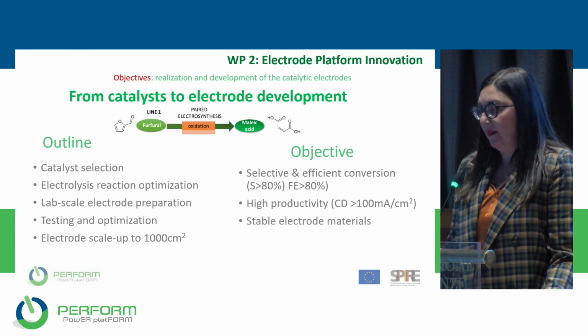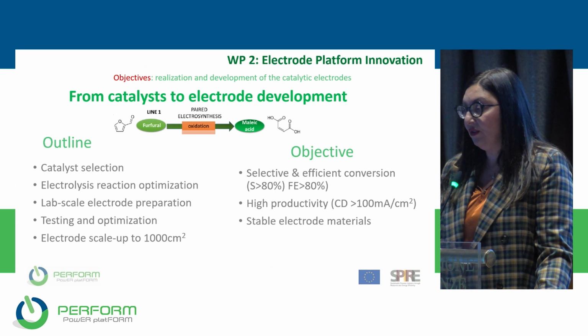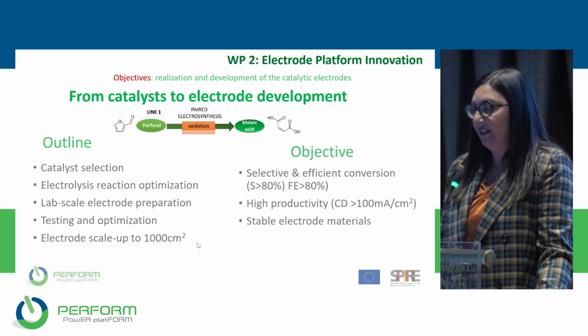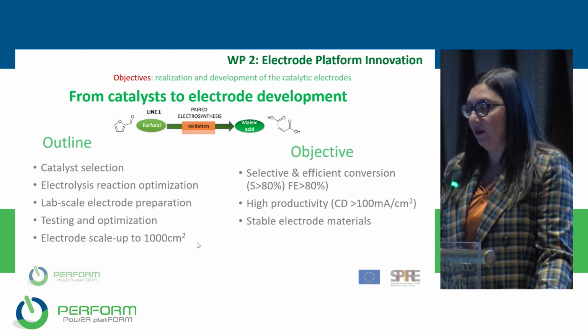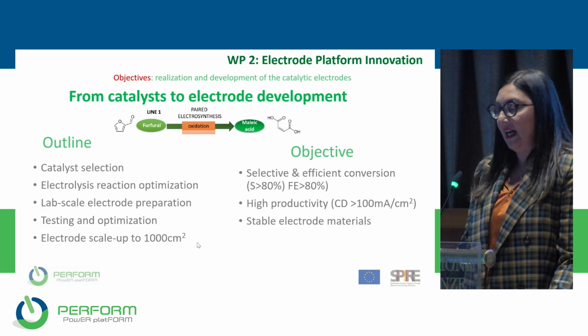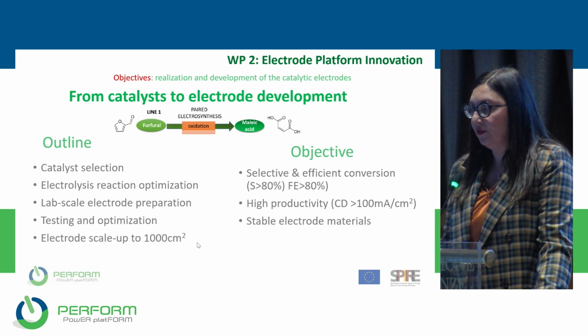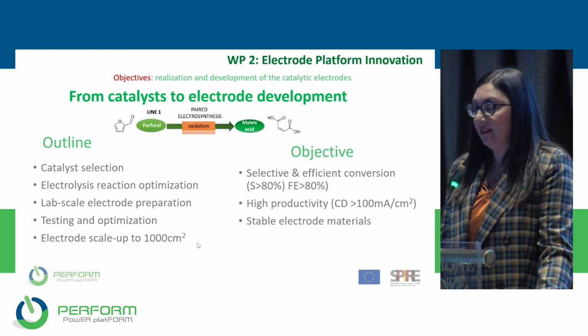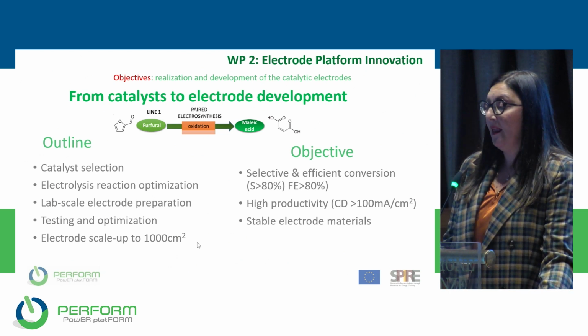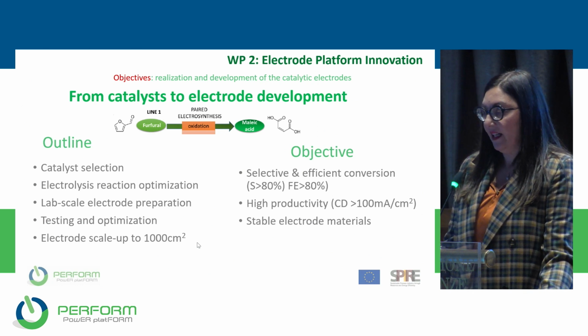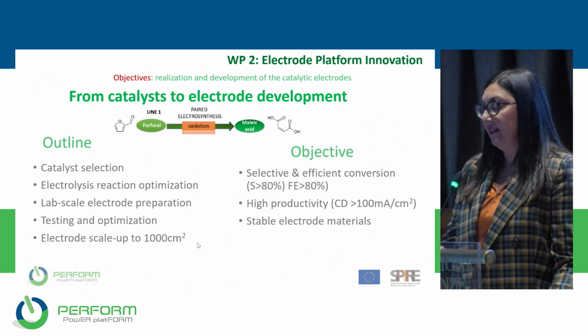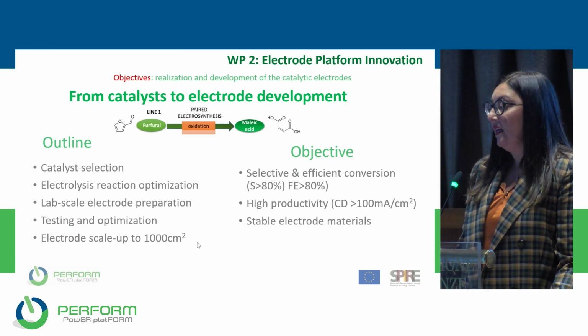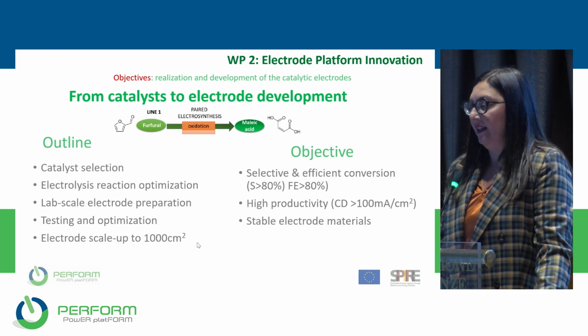And we start from the catalyst selection, and after various steps, we finally obtained an electrode that was able to run the oxidation of furfural and a system that has the characteristics that are suitable for its use in the successive step of upscale. So the requirements are essentially related to the selectivity and the efficiency of the reaction, the productivity of the system, and stability of the materials.